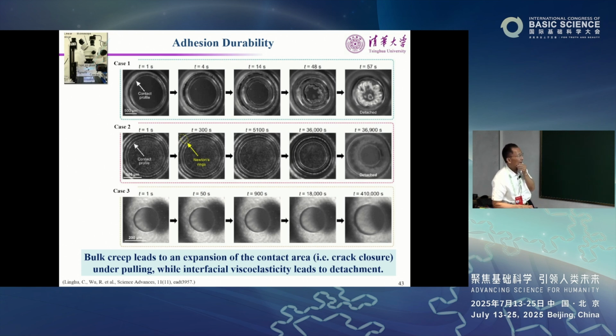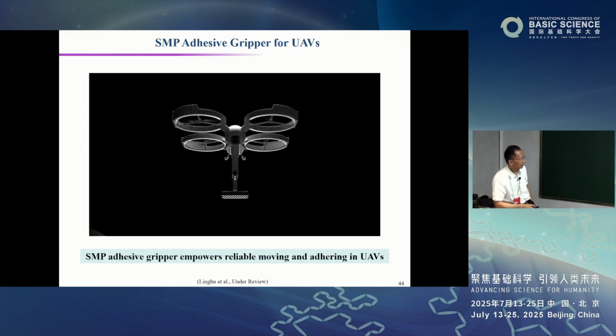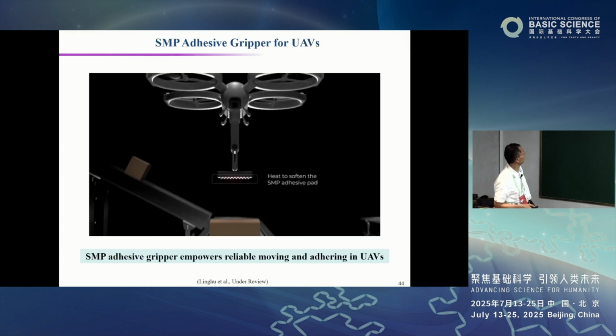As opposed to the other two cases, if the interfacial viscoelasticity dominates, then under pulling, you basically have delamination. The contact area decreases to 0. In case number 2, initially the bulk creep dominates, but then the interfacial effect becomes dominant at a later stage. So you have the three-way competition. If you can design a system such that bulk creep dominates, you can achieve permanent adhesion, right? That's no problem.